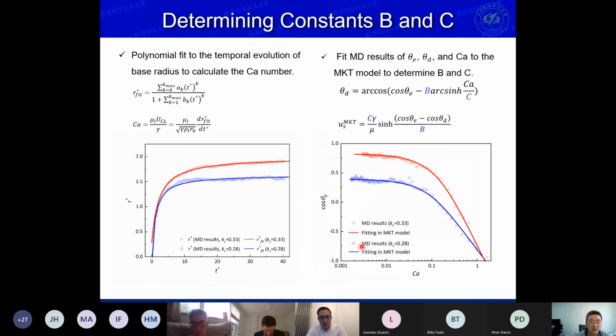And then we can do a polynomial fit to the temporal evolution of the base radius, and then we can determine the capillary number. After we have all the MD data of static and dynamic contact angle and the capillary number, we fit to the MKT model, and we can determine the parameters in this model. Actually, we use the dynamic contact angle model to fit, but when we use it in the VOF method, we don't use this. We just use the velocity of the contact line in this way.